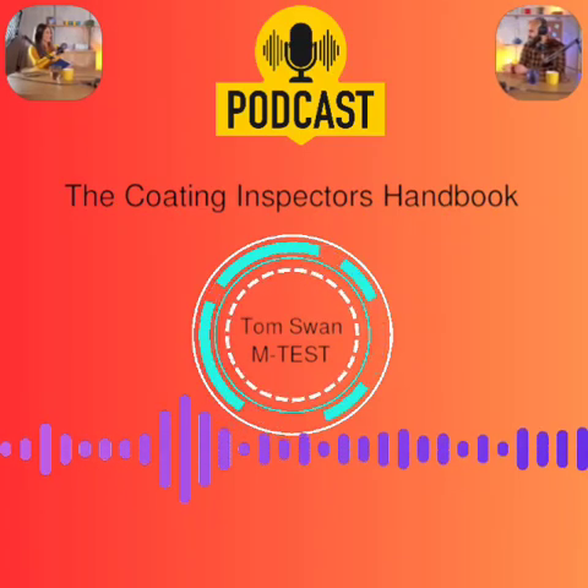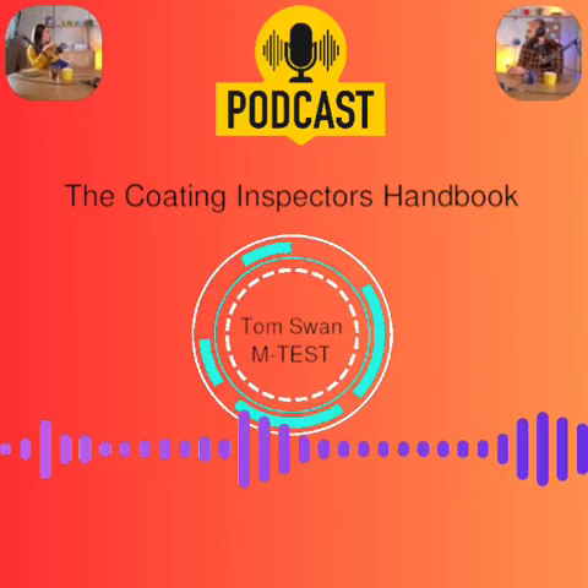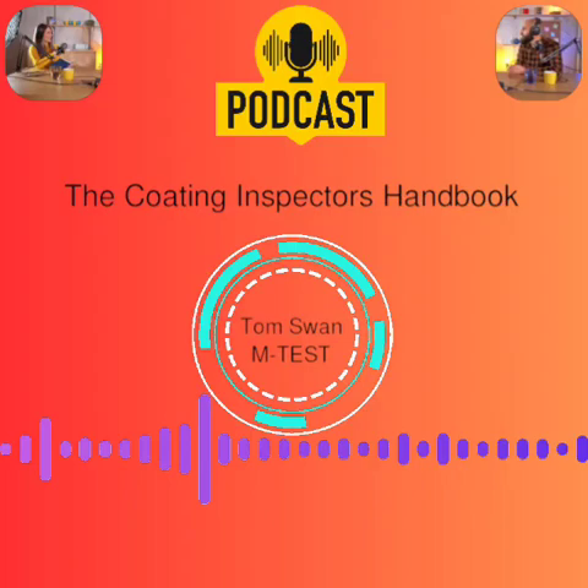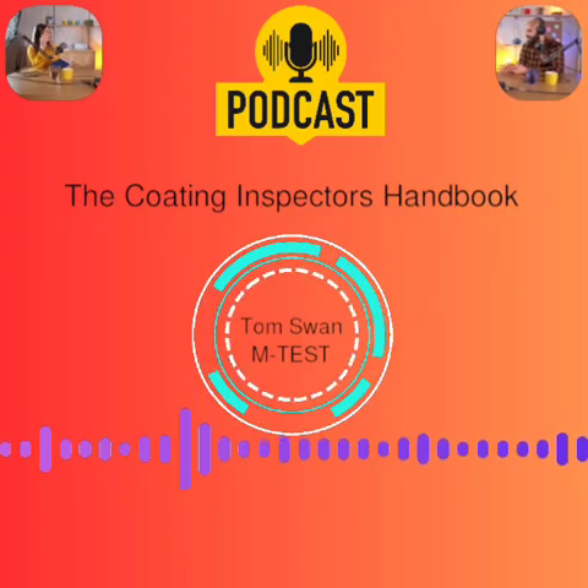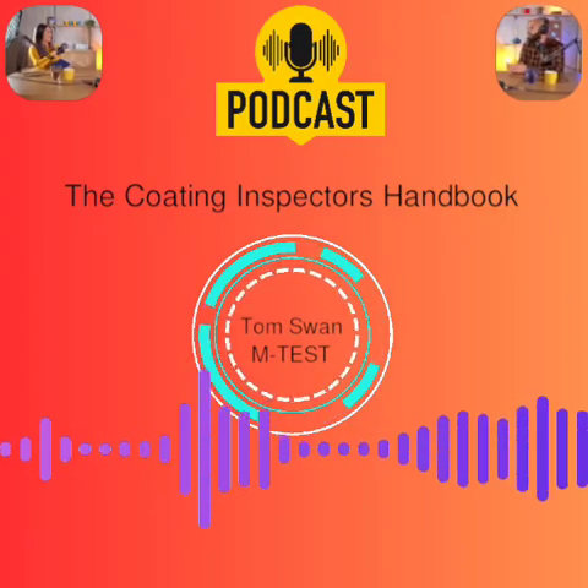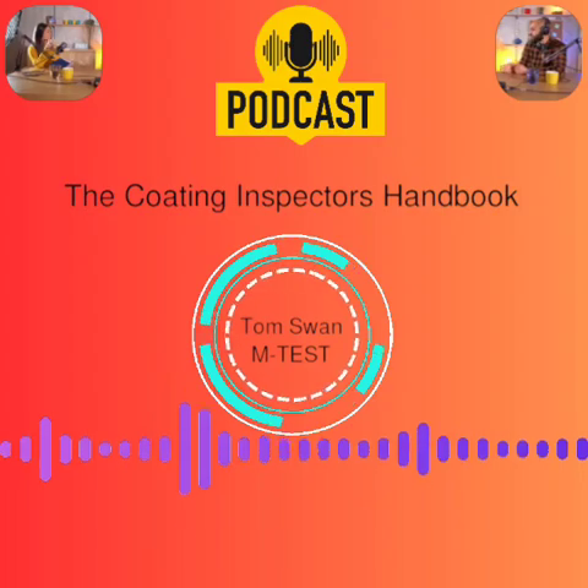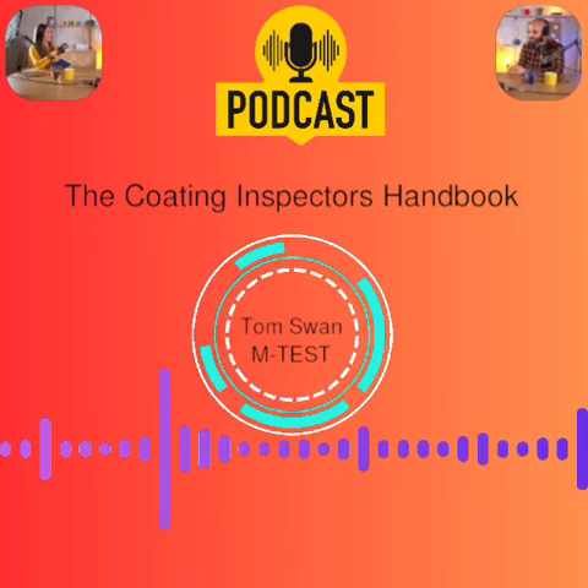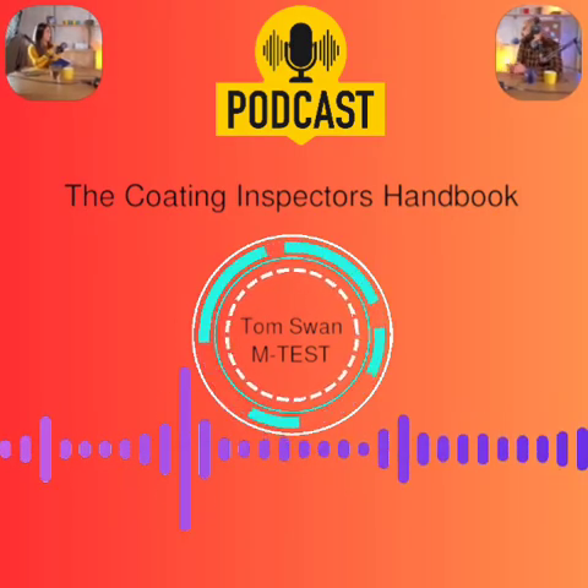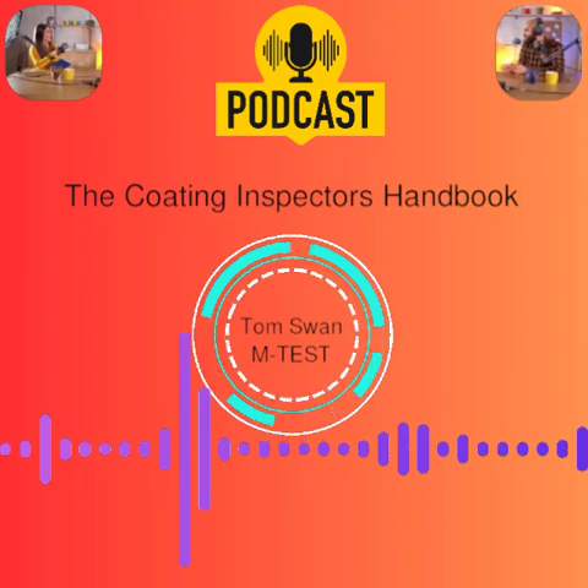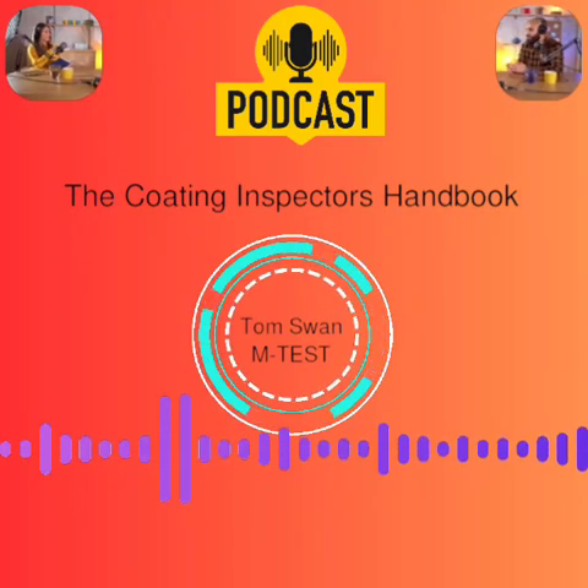How often do you verify calibration? Manufacturer calibration is usually annual. Verification is what you do on site. Type 1, verify each use on known shims, subtract BMR. Type 2, PA2 says verify beginning and end of each shift using shims on the actual uncoated prepared substrate you're working on, and must zero Type 2s on bare, non-ferrous substrates.